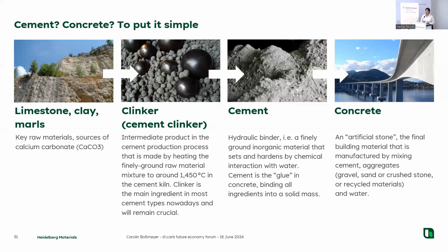With a temperature of 1,450 degrees heating. You can see the gray nodules there, that is the cement clinker on the second picture. The cement then is the gray powder that you may know.